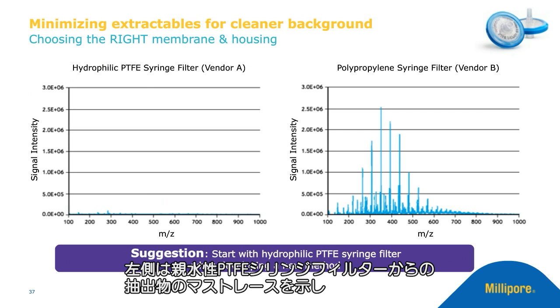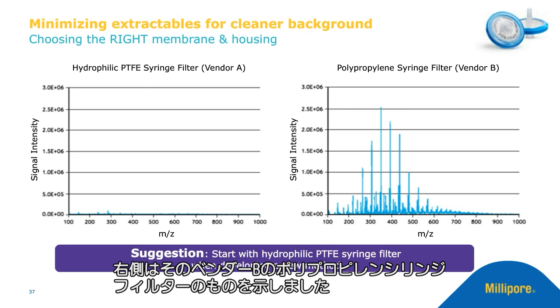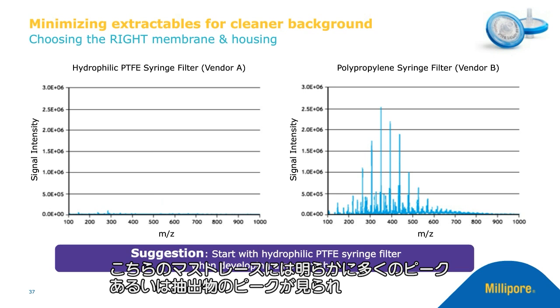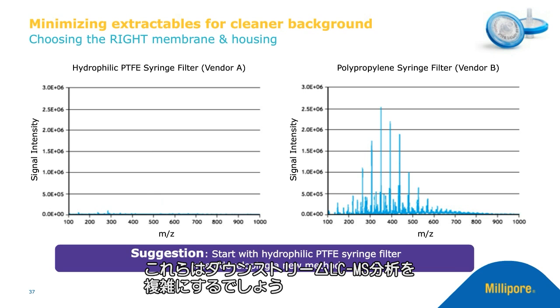On the left-hand side, I'm showing the mass trace from extracts from hydrophilic PTFE syringe filters, whereas on the right-hand side, you can see the polypropylene syringe filter from vendor B. And you can clearly see that there are a large amount of extractable peaks in this mass trace, which can become complicated during the downstream LC-MS analysis.